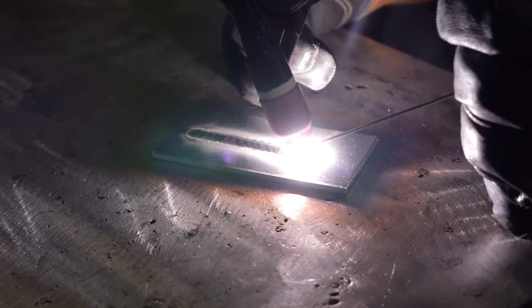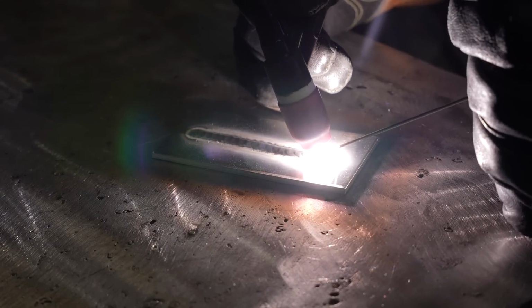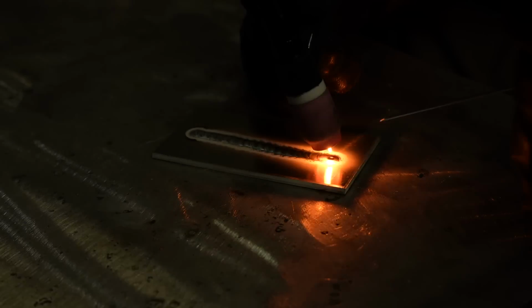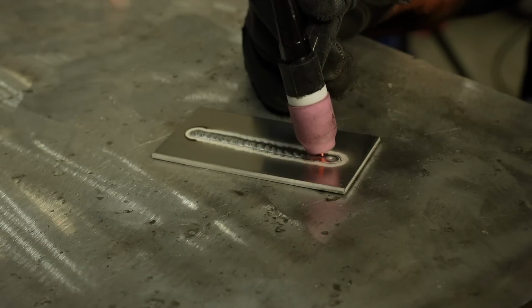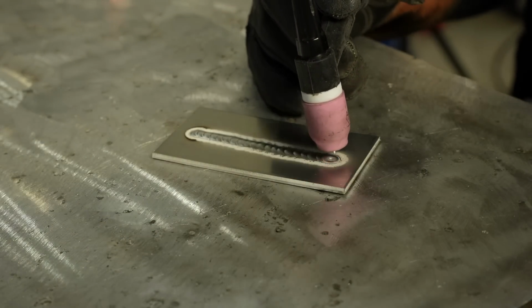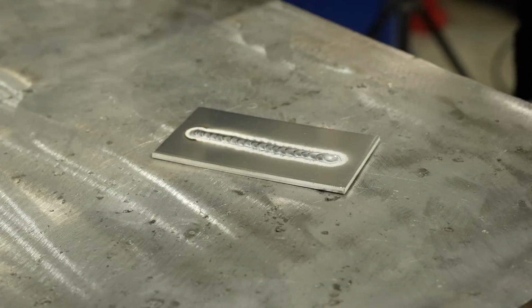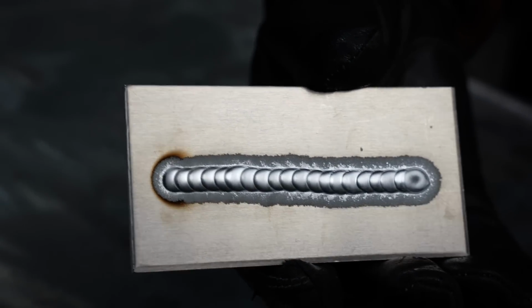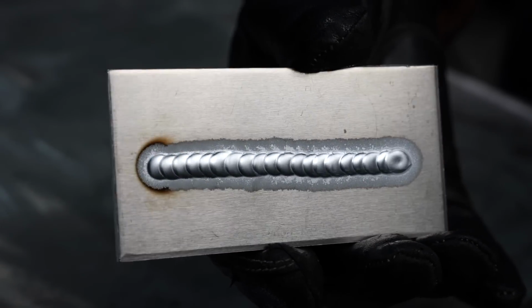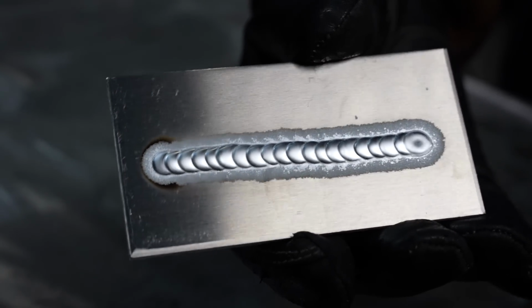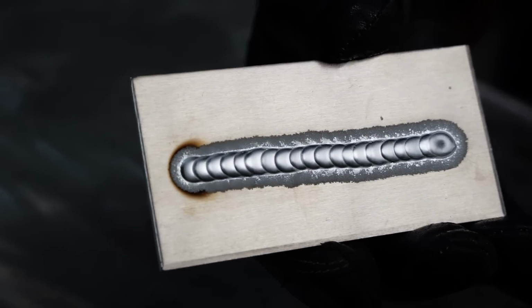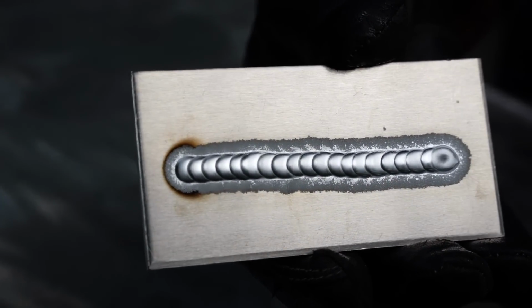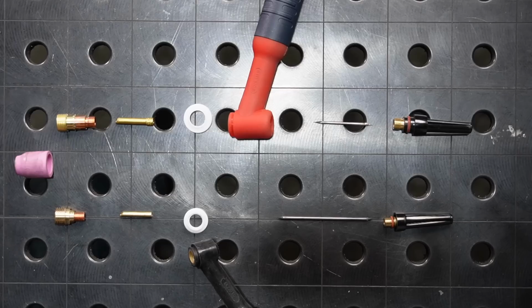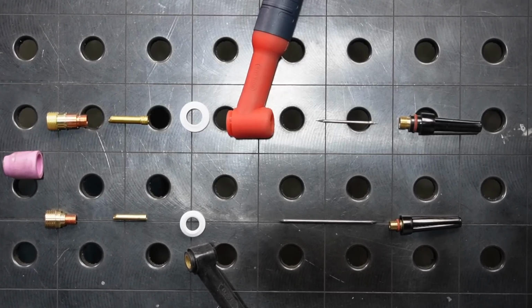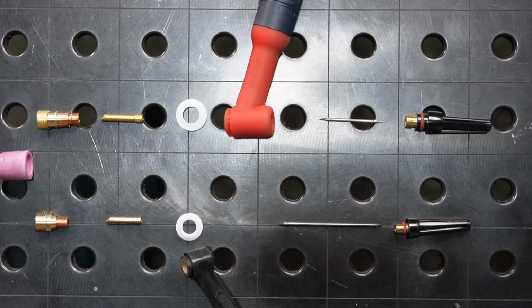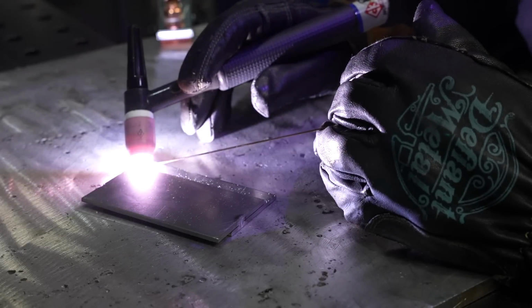In fact, I like to use a 7 or an 8 on aluminum sometimes, depending on the joint, instead of a small cup ideally. So it works for all 3 materials. Let's take a look at the finished bead here up close, and you can see it came out plenty clean enough, perfectly acceptable there. And you can also see that the etching band is a little bit wide from where the argon covered.